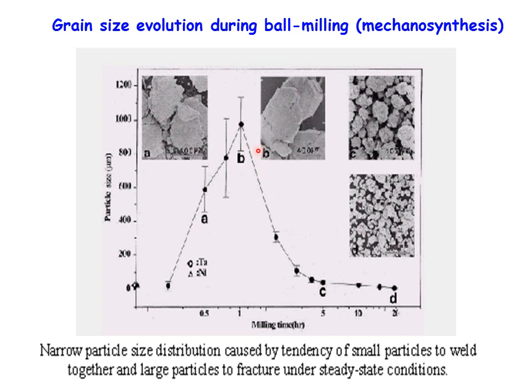And then these coalesced particles start to break, and we can reduce the size further. So if we start from here, for instance, ball milling will be pretty efficient. We have to wait 5-6 hours, and then we get much smaller crystallites. Starting from here will be perfect because from the beginning we start to reduce the size quite rapidly. But if you start from something like that, ball milling is going to be useless because after days of milling you will get exactly the same size.